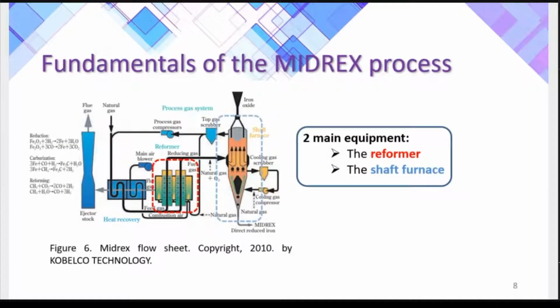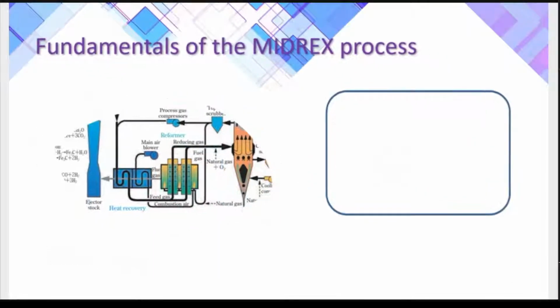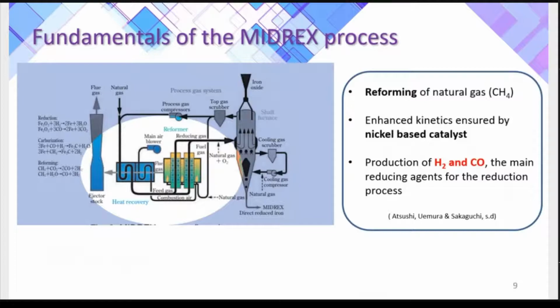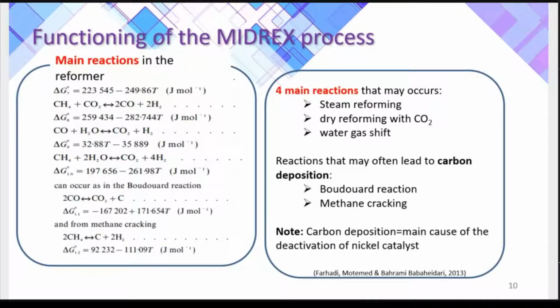So these selected pellets will go through the Midrex process. The Midrex process is composed of two main pieces of equipment, the reformer and the shaft furnace. The goal of the reformer is the production of H2 and CO through the reforming of natural gas. The kinetics of the reactions are enhanced by a nickel-based catalyst, and the natural gas will react with CO2 or water as steam reforming, dry reforming, or water-gas shift reaction. Some reactions may lead to carbon deposition, such as the Boudouard reaction and methane cracking. And as we know, carbon deposition is the main cause of the deactivation of nickel catalysts.